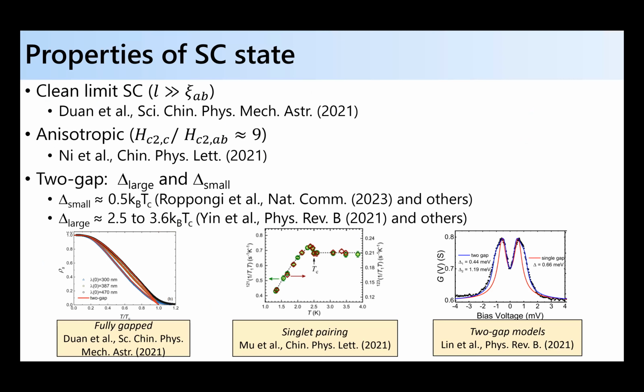As you know, JP, one gap is small, the other gap is large. It's singlet pairing from this Hebel-Slichter peak that's been seen by NMR. So I think two gap models are the predominant ones. So the two gap data is from STM or? This is from soft point contact, but I think also penetration depth, specific heat, lots of probes that are just fitting with two gaps.